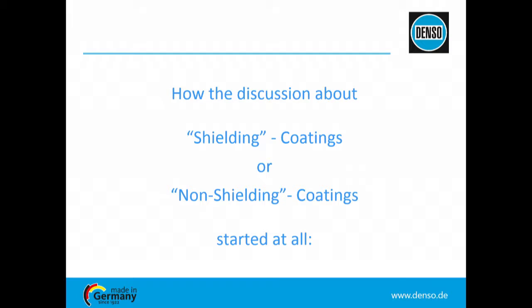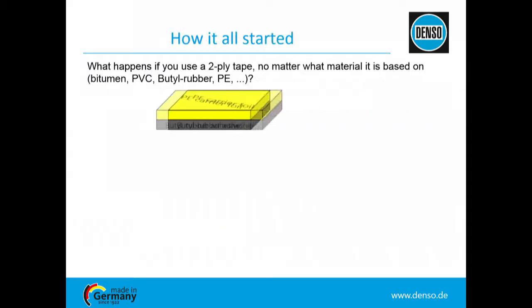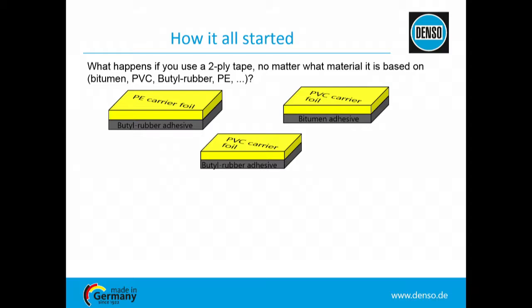So now, coming back to the initial topic of my talk: what about the discussion about shielding coatings or non-shielding coatings? How did it start at all? In the 60s, or until the 60s, bitumen-based coatings were often used on pipelines in Europe. Then in the 70s, one decided to use newer, modern materials based on plastics, on polyolefins like polyethylene carrier foil or PVC carrier foil, with an adhesive based on butyl rubber or even also a bitumen rubber adhesive. This was the first step of development, of improvement compared to pure bitumen, because bitumen was well known to become brittle with time and to lose its properties. So after a decade, it's not in good shape anymore.